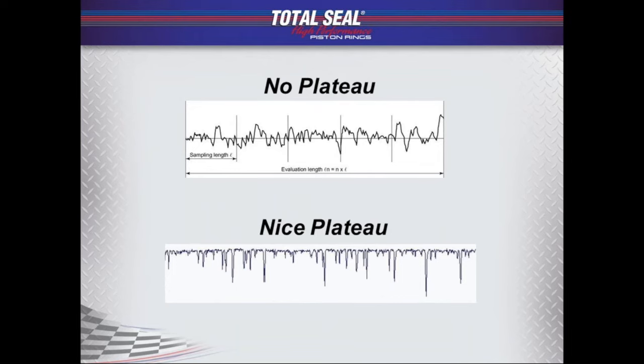And again, this is kind of a reflection of the same surface finish we just looked at. The above up here, if you can see the pointer, we've got no plateau, got lots of peaks. This is our Rk, this is our core value, this is our valley, but we don't have what we've got down here, a nice plateau, that nice flattened out surface finish. And that's what's essential to getting good, quick ring seal today with thin rings, hard coatings, and hard blocks.